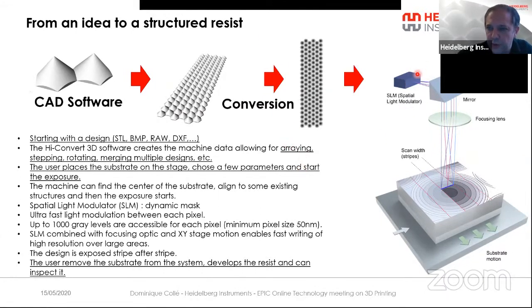Like I said before, the spatial light modulator is acting like a dynamic mask and can do modulation of the light intensity in a very fast manner. For example, we can change from 0 to 1 in a few nanoseconds. And then we can use up to 1,000 gray levels that are accessible for each pixel. And the pixel is basically the positioning of the beam, and the minimum position that we have for the dose, like a change of dose, is into a 50 nanometer grid.